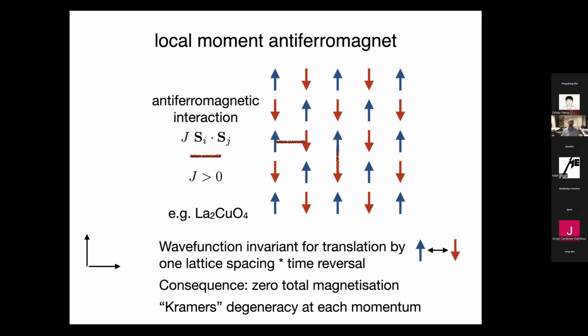And in the band structure, I also find a net total magnetization. Now let's look at an antiferromagnet. I consider the same square lattice, but now the interactions are antiferromagnetic and between nearest neighbors. So my exchange constant is larger than 0, and I have a standard two sublattice antiferromagnetic order, as is, for instance, the case in lanthanum 2 copper O4, the mother compound of the high-Tc cuprates.